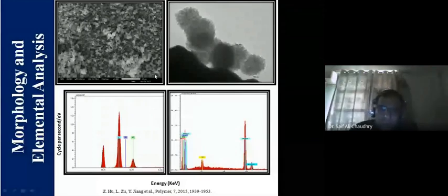Then EDX was used to know the elemental composition of the composite. That is, carbon, nitrogen, and oxygen were there in the pure black cumin. But after the composite formation, manganese appeared, indicating the presence of manganese on the surface. And unfortunately, one peak corresponding to potassium also appeared, because we used KMnO4, and that potassium from the KMnO4 got trapped into the crystal.